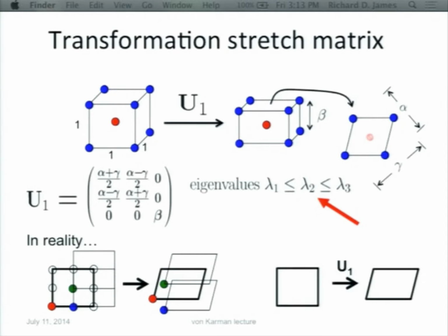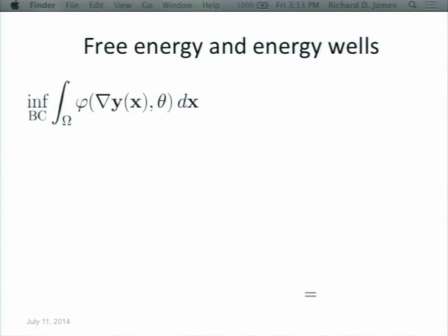This is a small remark, but it's an important remark. In reality, we actually deal with complex crystals, which are the union of many Bravais lattices. In the example at the end of my talk, there will in fact be 18 Bravais lattices. Each one undergoes the same linear transformation during the transformation, but there are displacements between the lattices. In that case, the linear transformation is defined as the one associated with any one of those Bravais lattices.